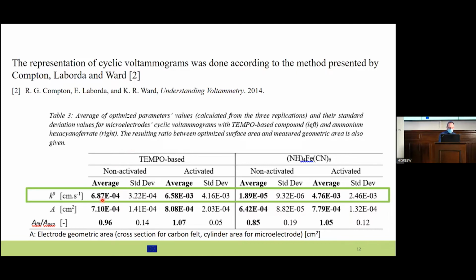Just to give the range, we are in the range of 10 to the minus 4. After activation, we reach this range of 10 to the minus 3, the target of HIGREEW. Then here for the hexacyanoferrate, we are much lower. Before activation, we have 10 to the minus 5 centimeter per second, and we improve significantly by activation. So activation of the electrode is useful.